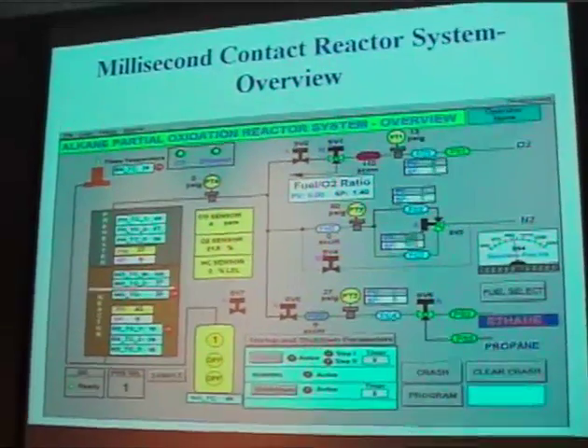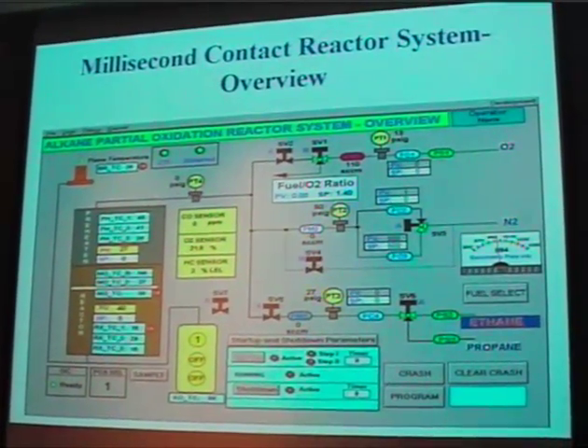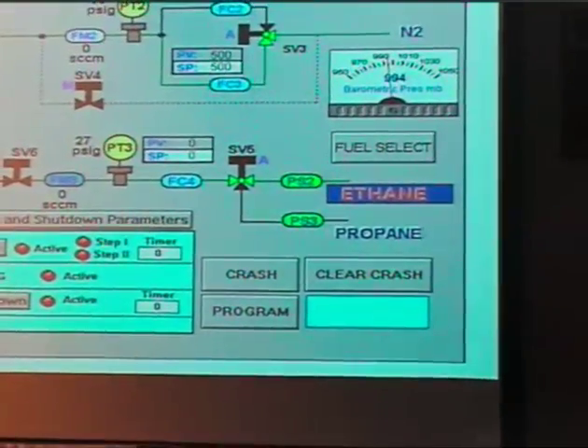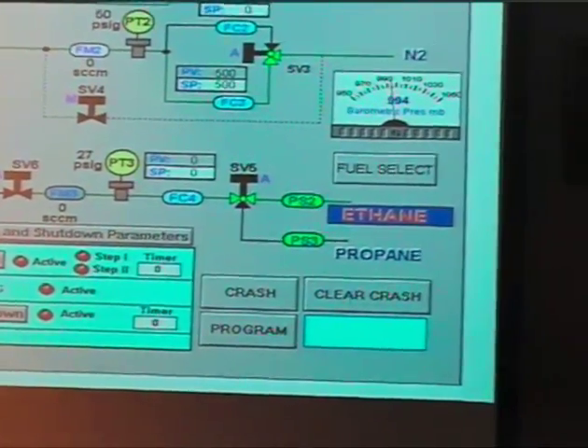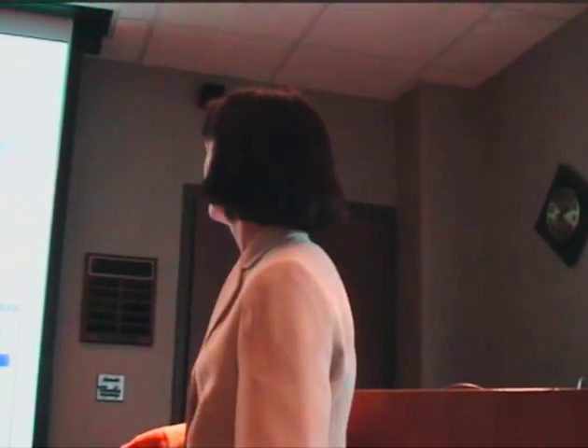Starting up, we ran not only methane for oxidation, but we looked at ethane and propane for the oxidative dehydrogenation activity. And a lot of times it was beneficial actually to begin the unit up under propane because the catalyst would ignite at a lower temperature and then you could slowly blend out the propane and replace it with methane. And so all of this was automatically controlled with a program to safely get you up to your running conditions.